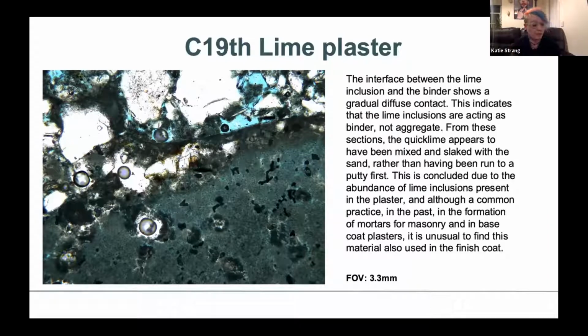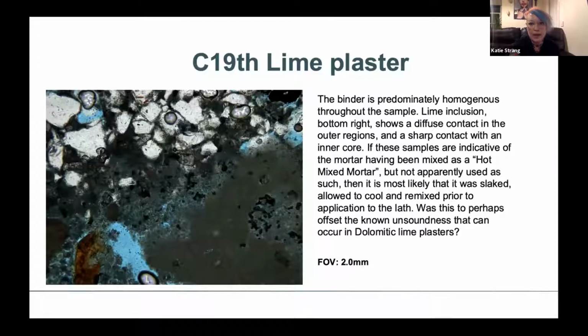And in plasters, normally you have a finishing coat on your plaster, which is gauged with gypsum. And quite often it can just be a pure gypsum finishing coat. But on this one, we could see evidence of quicklime within the finishing coat, which is very, very rare. It's just not exactly the nicest material to get that flat finish that you want with your gypsum. This image here again shows another lime inclusion. And as I said, if these have been mixed as a hot mix mortar, it doesn't look like they've actually been used in that way. So they weren't used straight away when they were hot.